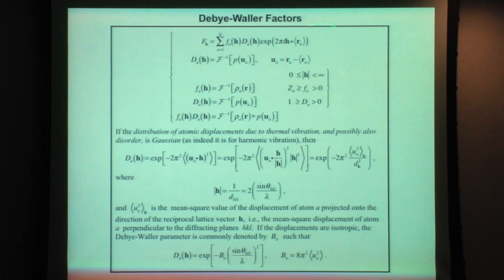And then it is multiplied by the exponential of 2 pi i times (h dot x plus k dot y plus l dot z), where x, y, and z are the coordinates of the atom A. So there's a position vector for each atom A, which has x, y, z components.